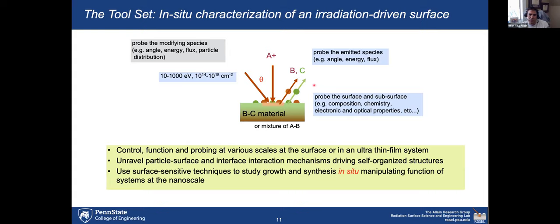And then finally, in addition to that, we complement those techniques with techniques that are able to probe the emitted species. As it turns out, the energetic particles that are interacting with the surface are not only going to drive changes to the surface itself, but there are going to be reactions in which some of these species are emitted from the surface. They can be sputtered. They can be sublimated. And in doing so, those particles are going to carry information about the mechanisms that are at play. Could be their energy distribution, their mass distribution, et cetera. So all these techniques have to be conducted in situ. They need to be conducted while you're doing the irradiation. That is the premise and the design of our experiments.